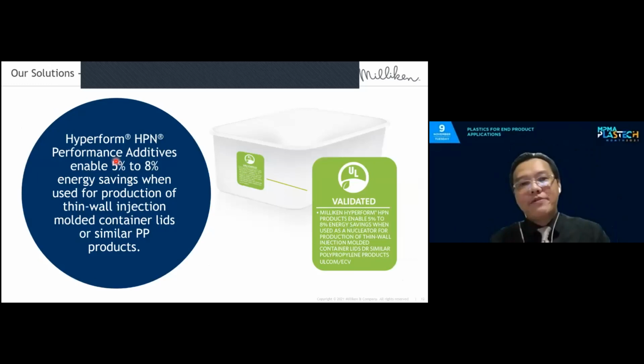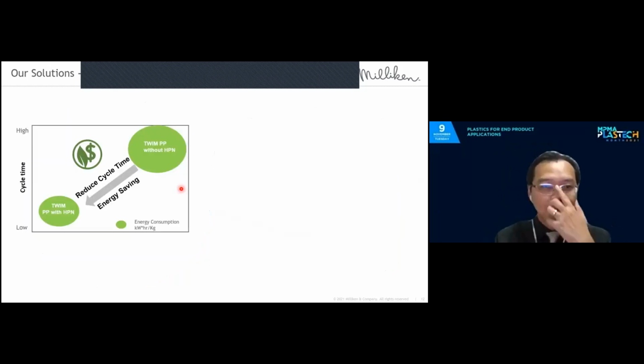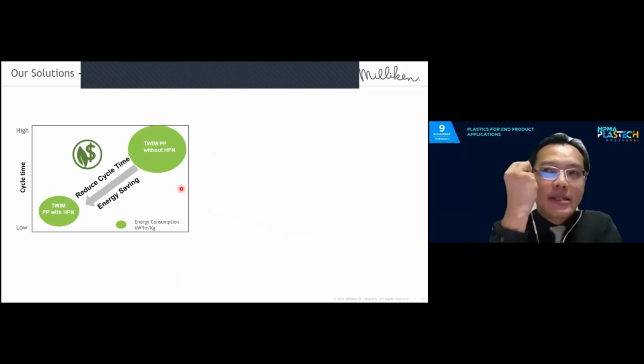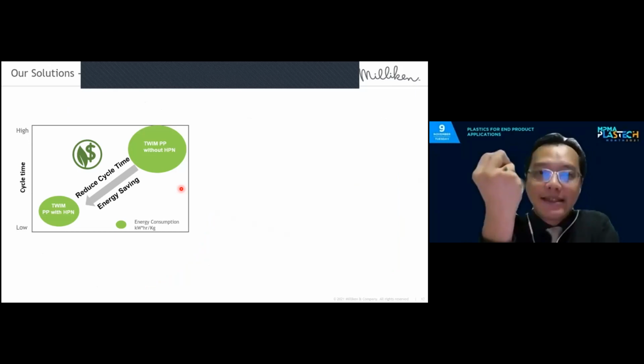Now we move on to Hyperform. It is very similar in concept. This is mainly more for homopolymer and impact copolymer. Apologies, homopolymer and impact copolymer. And we have again worked with Underwriters Laboratory. So an example here is for thin wall injection molding, where again the HPN, the Hyperform, enables this 5 to 8% energy savings. And this time it is mainly about the core effect of the nucleating agent.